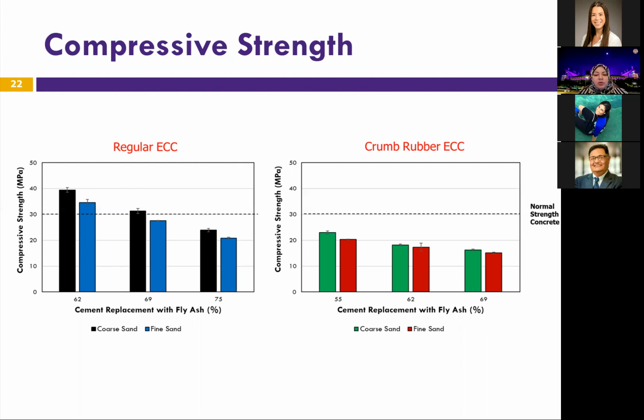We also saw that increasing the percentage of fly ash in the mix decreased the compressive strength. This can be attributed to the fact that the use of fly ash may limit the secondary hydration reaction of the fly ash at 28 days. We only tested at 28 days, but I believe that if we had left it longer and tested at 56 days, the compressive strength would have increased.